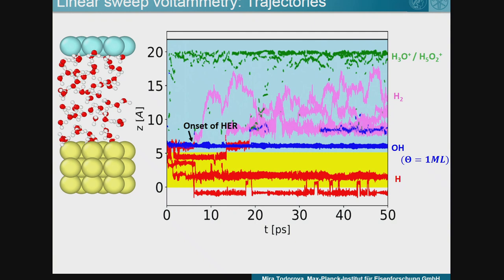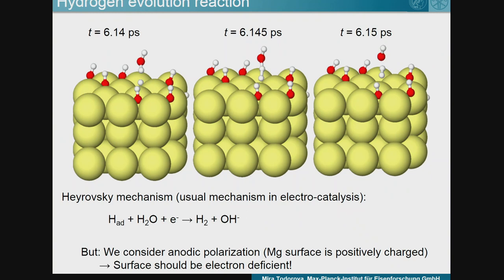So again, we have here dissociation of water and OH coverage. However, this time it reaches one monolayer. We also see that we form a hydronium ion, which as expected would move to the counter electrode site and screen the charge here. And what we were very excited to see is that we really see the reaction and the formation of hydrogen molecules within this system.